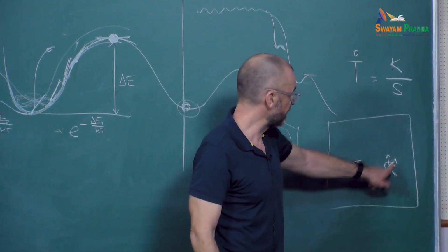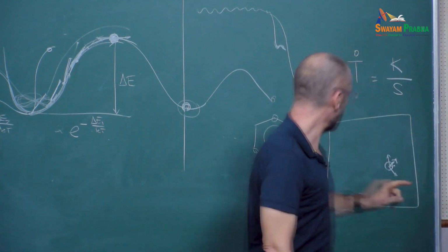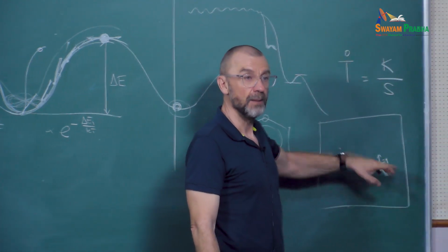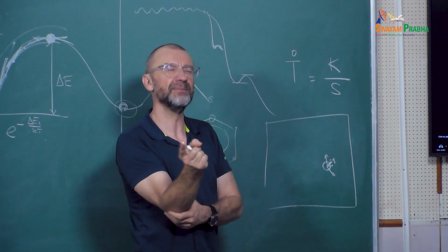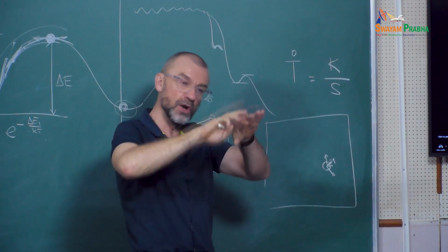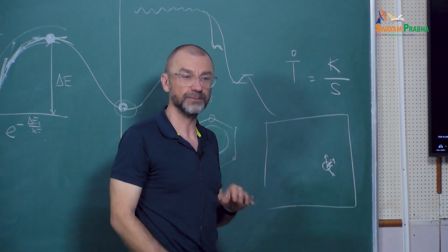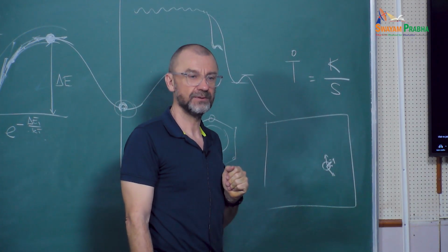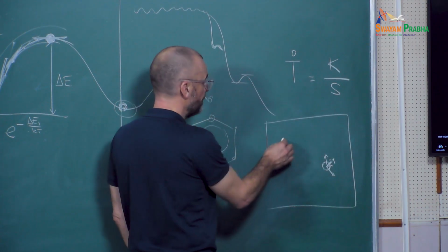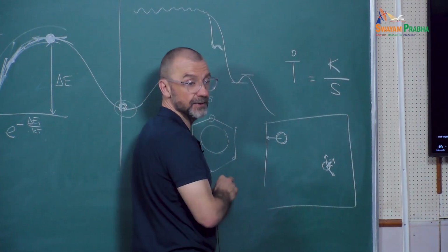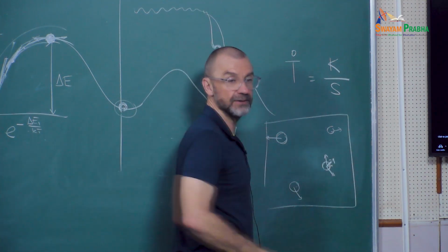And I use that random vector as my initial displacement. So initially, I only move one atom. But then as I minimize the energy and look for the eigenvalues, the eigenvector of minimum eigenvalue will involve the displacement of many atoms around that initial atom. Do I make sense? When I go back, I'm going to pick another atom and another displacement, and so on.